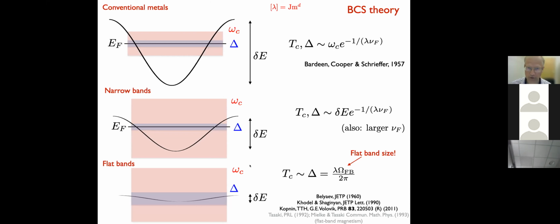Then you have other regimes which have also been considered recently, but are maybe not as well known. One is that of narrow bands. So we go towards flat bands. We take a bandwidth which is smaller than the characteristic frequency of the bosons. In this case, we get a similar expression as before, but replacing the cutoff frequency by the bandwidth. Typically, if you do this by shrinking your band, your density of states also becomes larger, which means that your delta and Tc are typically larger than in the previous case.